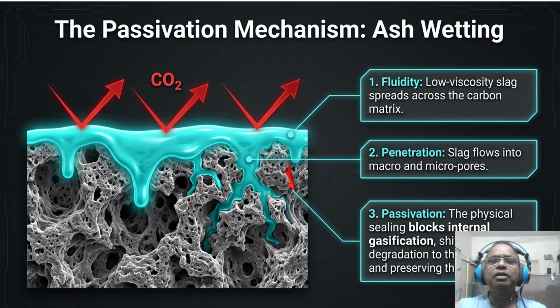Now coming to this slide on the passivation mechanism, how the ash wetting occurs. So imagine that low viscosity slag just spreading like water across the carbon matrix. You can see it, the fluid slag flows deep into the macro and micropores. This is a three-step process: fluidity, penetration, and finally passivation. By flowing into those pores, the slag physically blocks internal gasification. We are forcing all the CO2 degradation to stay on the outer surface, which preserves the structural skeleton, the core of the coke. So the big question is, does this shield actually keep the coke from shattering?